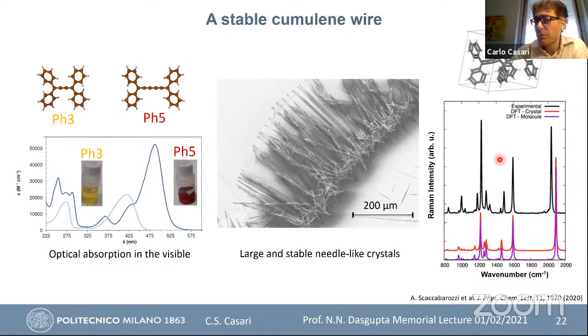Stable systems are very useful. In fact, by collaborating with Rick Tykwinski at the University of Alberta in Edmonton, Canada, he sent us these very nice systems. These are cumulene-like systems, so double, double, double, or almost double, double, double, because the termination is affecting the structure. And these terminations are able to stabilize the system. They are very interesting because the optical absorption is in the visible, not in the UV. And you can see that by changing a couple of carbon atoms in the chain, you shift from yellow to dull red.